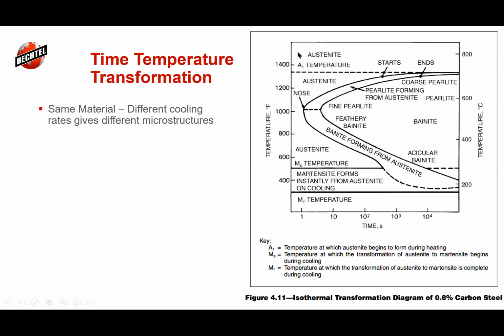So when we look at a time temperature transformation diagram, everything above this dotted line is austenite. It's heated up enough, red hot, whether it be weld metal or the heat affected zone, it's heated up and transformed. Now you can superimpose a line, and normally I have one. I apologize, I don't have one. But if we cool this down extremely fast, if we quench it in less than 1 second, we would cool from austenite and we would hit this martensite temperature. And then you form martensite. And this is when we talk about welding with a 60-10 or arc strikes on this material. What we're really doing is heating that material up extremely quickly, letting it just quench. And so that's the same action as cooling right down very, very quickly.